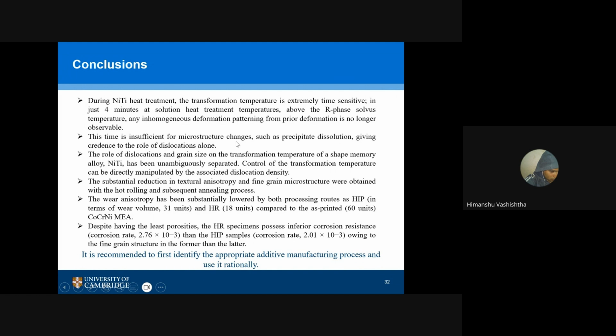Time was insufficient for the microstructural changes, and for the precipitation dissolve as well. So we are claiming that whatever the transformation temperature changes or whatever we are getting, it's solely responsible for the dislocations only, right? Not because of the grain size or any precipitate, because we have not given sufficient time to do anything with the grain size or the precipitate. So it was solely responsible for the dislocations only.